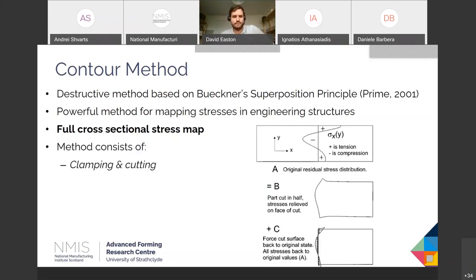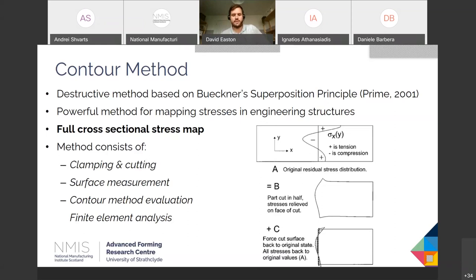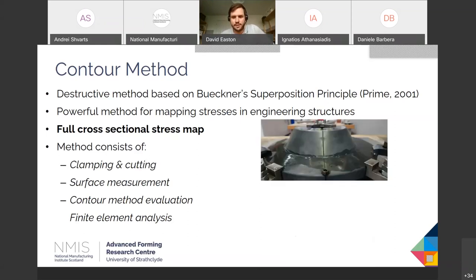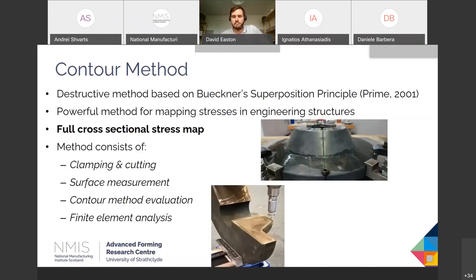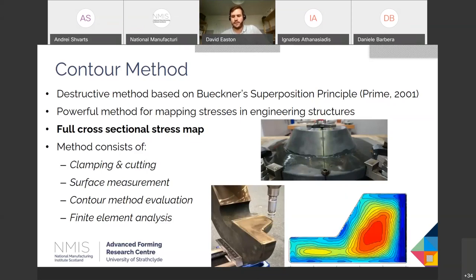The method consists of clamping a part, cutting it using EDM, measuring the surface using a CMM or optical methods. We then apply our contour method evaluation, and finally some finite element analysis. So here in a disc type component, we can see it's been sectioned by EDM. We then measure that cut surface and we can calculate that whole residual stress field. Getting this sort of density of data would take a long time using other methods.